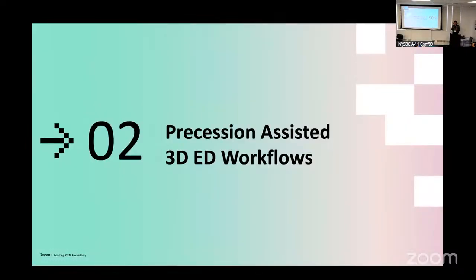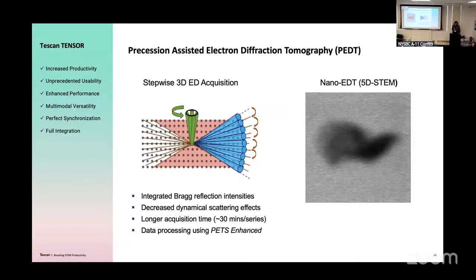What they had in mind is basically to automate data acquisition, to make an instrument which can be used even by inexperienced microscopists. And so they implemented a lot of workflows, including precession-assisted electron diffraction tomography, again, another term. And Peter Oleynikov from Nanomegas will speak much more about it, but it's basically at each angular tilt, you take a precession image, so you have better integrated Bragg reflections, and you decrease the dynamical effect.